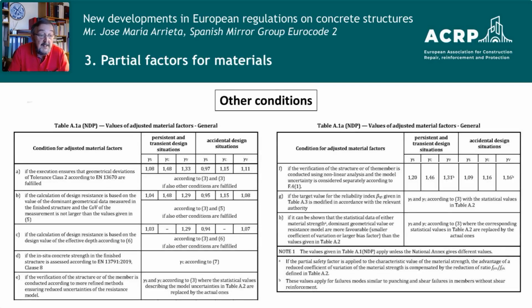We have a list also of different typical conditions, many of them related to existing structures. For example, condition B refers to whether we measure some geometrical measure. If we measure the geometry, for example the depth, we can reduce the coefficient. For example, you can see gamma_S may be 1.04 instead of 1.15.